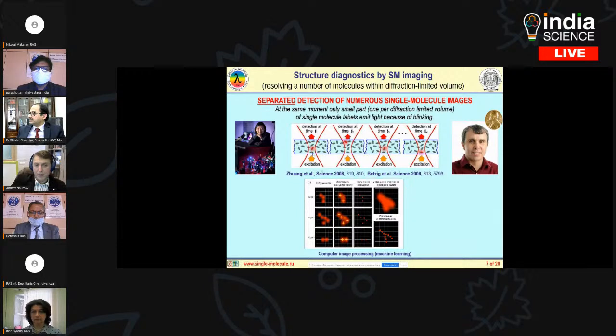We can look at the molecules which emit light only at certain moments of time. For example, we can switch on and switch off the luminescence by an additional laser. As a result, if we have a proper concentration of these labels, at each time moment we will have in each diffraction limited volume only one emitting molecule. For example, like here, we have some sample, and we have a lot of label molecules, like here.